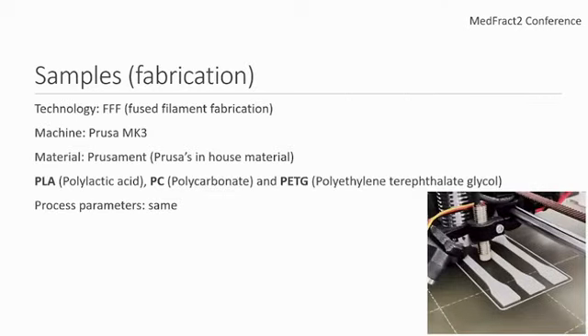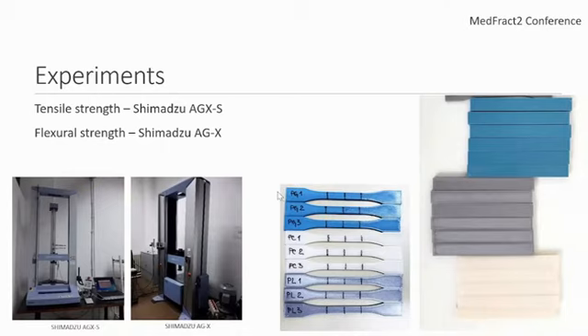We used the fused filament fabrication process, with the Prusa MK3 machine and the Prusa in-house material Prusament for obtaining the best results. The three materials we are comparing are PLA, polylactic acid, PC, polycarbonate, and polyethylene terephthalate glycol, or PETG. We used the same process parameters for all the samples, except the temperature that is needed for the different materials, and we did not change any of the process parameters during the fabrication process. For the experiments, we used Shimadzu machines, the Shimadzu AGX-S for the tensile strength and the Shimadzu AGX for the flexural strength.